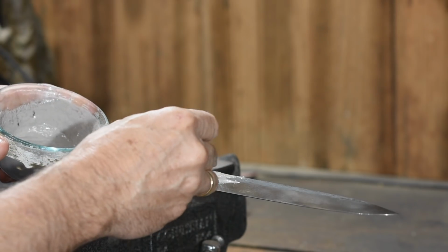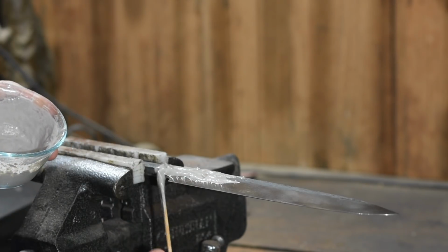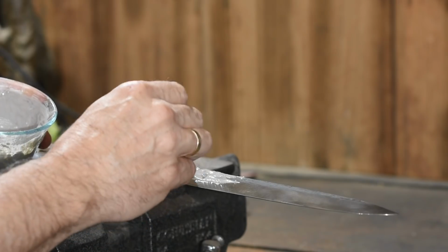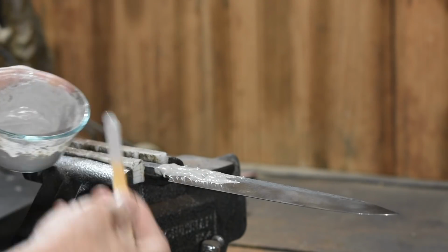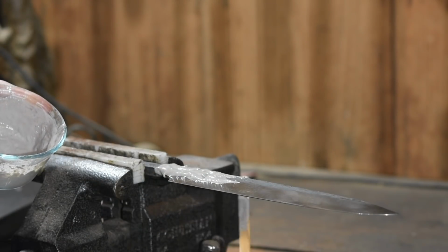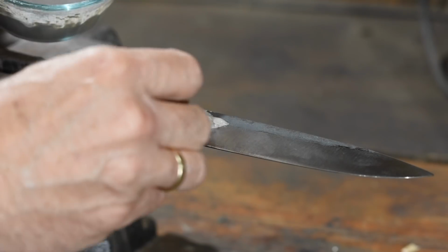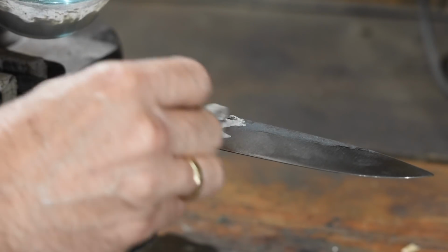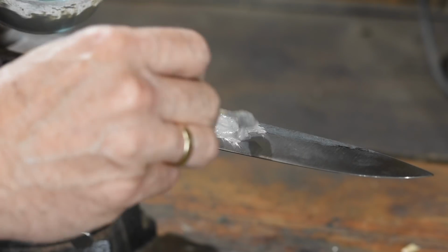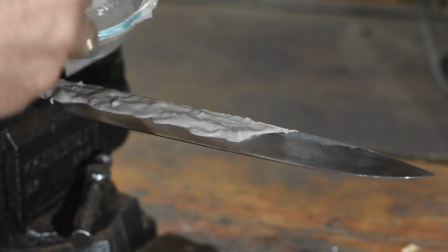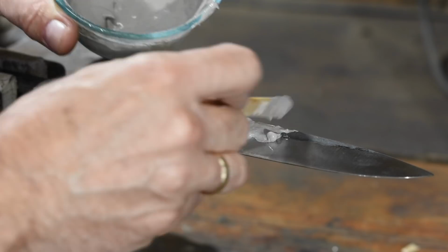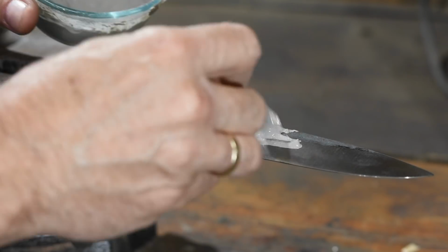Carbon steel is hardened by heating to about 1500 degrees and then rapidly cooling the steel, which causes the crystalline structure of the blade to reconfigure into a very hard structure known as martensite. The clay acts as both an insulator and a heat sink so that the steel that's covered in clay doesn't cool quickly enough to harden.